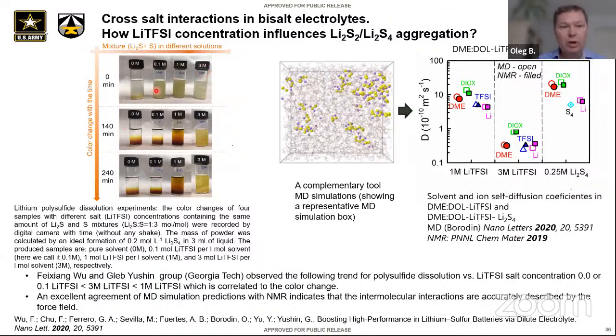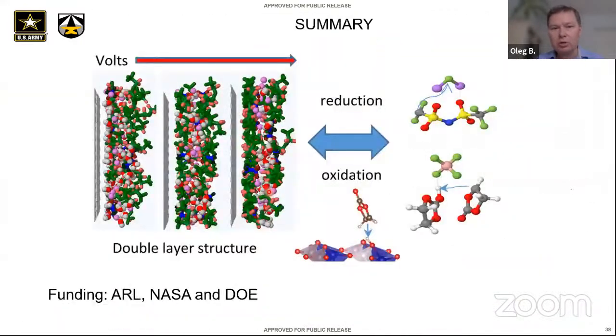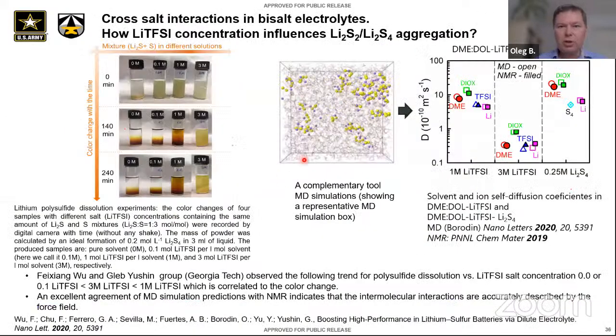What they did observe is that 0.1 molar had the lowest solubility, and also, despite the lowest viscosity, the fastest electrolyte. Solubility was low, and also the dissolution process was slow. 1 molar was the fastest, and 3 molar was the intermediate one. So I did, in a joint collaboration with them, perform MD simulations, took again Li2S2, Li2S4, and combined mixtures, and put both in MD simulation,